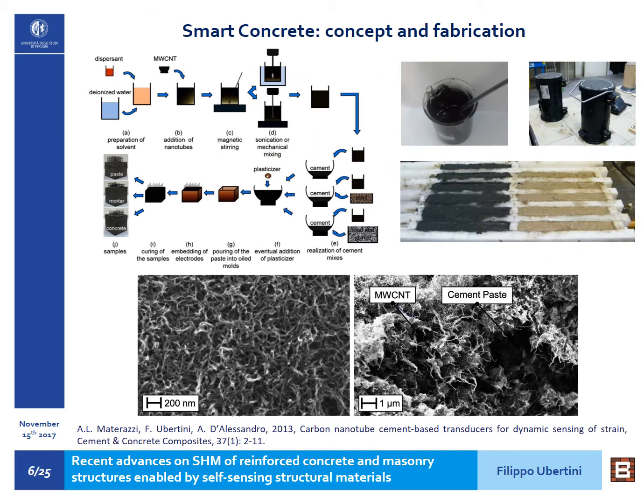So here you have a few highlights of how we fabricate smart concrete and smart concrete sensors in our lab at University of Perugia. On the top left you see the fabrication procedure, where we first disperse the nanotubes in water by using tailored chemicals that are called dispersants. Then we improve dispersion of nanotubes through magnetic stirring, and in most cases through sonication and mechanical mixing. Then we add the aggregates and the plasticizer to improve workability. We cast the composite into oiled molds, we embed the electrodes, and at the end we have these cubic smart sensors made of cement paste with nanotubes, or mortar with nanotubes, or concrete with nanotubes.